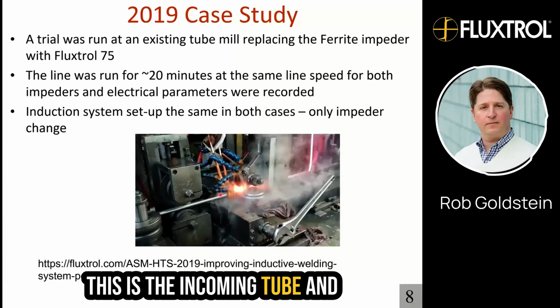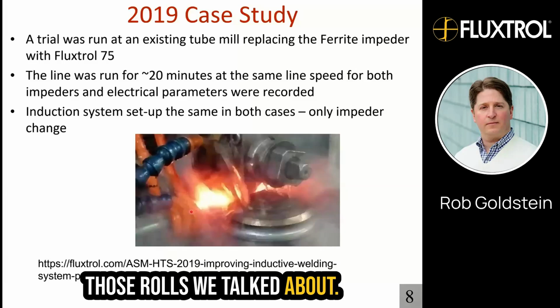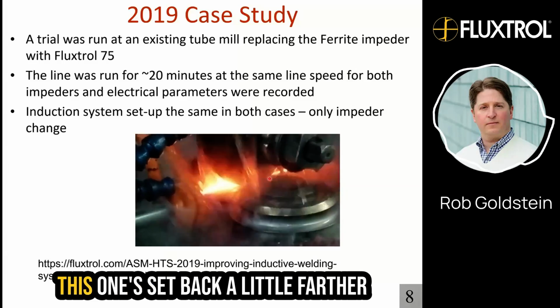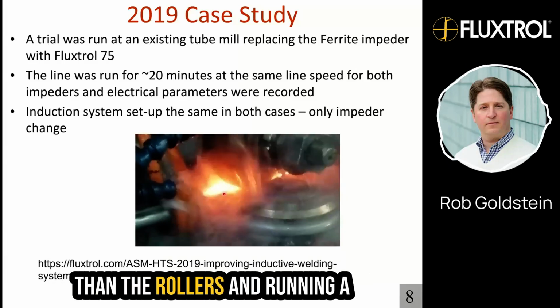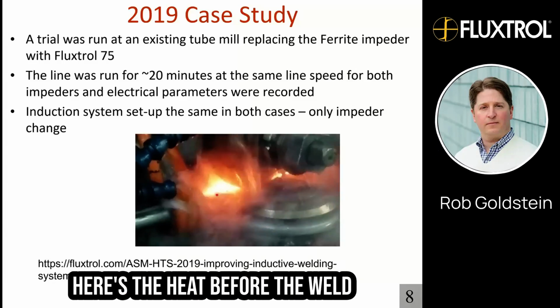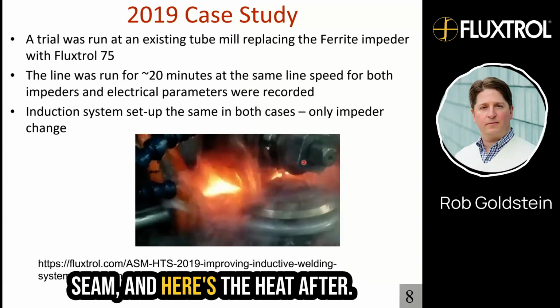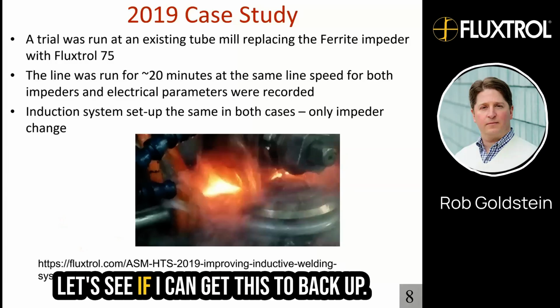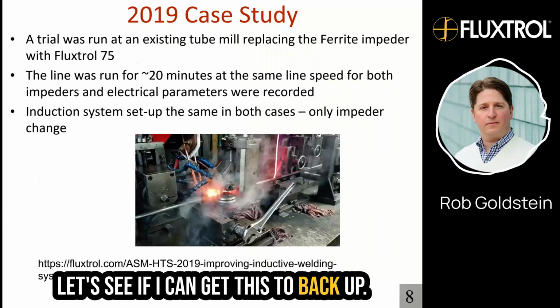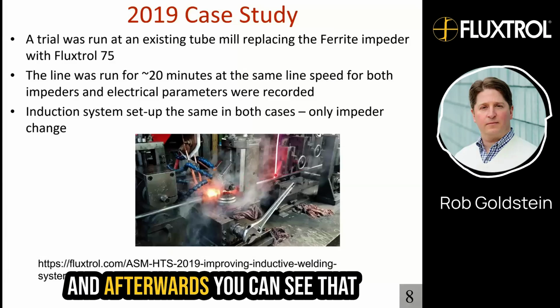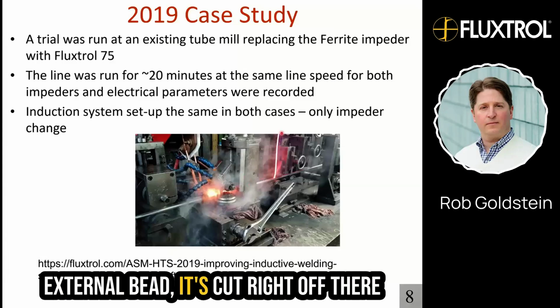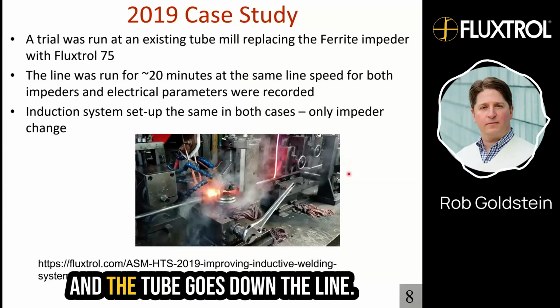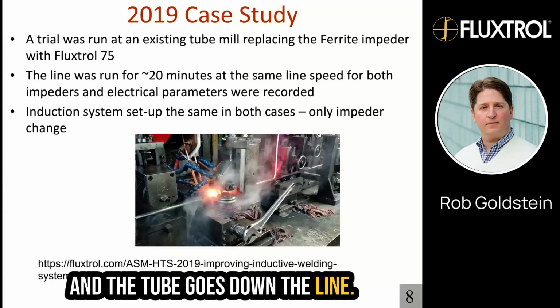This is the incoming tube and those rolls we talked about. Here's the induction coil. This one's set back a little farther than the rollers and run a little hotter than the other. But here's the heat before the weld seam, and here's the heat after. Let's see if I can get this to back up. And afterwards, you can see that external bead is cut right off there, and the tube goes down the line.